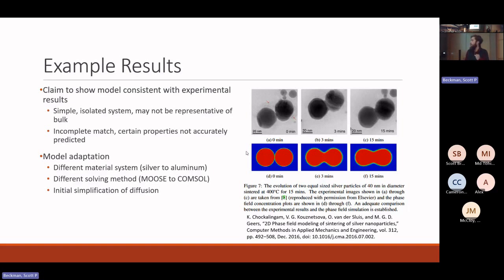It did not include quite a few things that I believe I talked about on a different slide. But as a result, it's not a direct match and there are significant differences between the experimental and theoretical results. Additionally, because this was such a simple isolated system, it might not be representative for larger sintering processes that involve more than two particles.